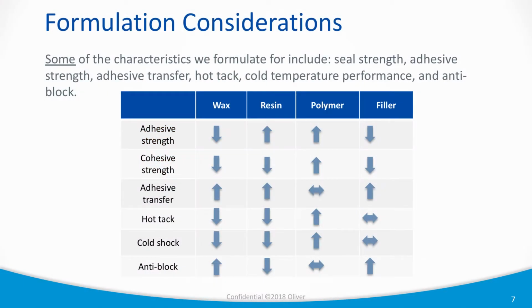So here, this is a kind of an overwhelming chart, but basically if you look down the left side, there are different properties, and the formulation ingredients are on the top. So it basically shows, for example, we're concentrating right now on the cohesive strength, because that's what's getting our peel strength. So for cohesive strength, if you increase the wax, it'll decrease cohesive strength. If you increase the resin, it'll decrease the cohesive strength. If you increase the polymer, it'll increase the cohesive strength. So the arrows are giving you the direction that each component will get you generically. Filler will decrease the cohesive strength.